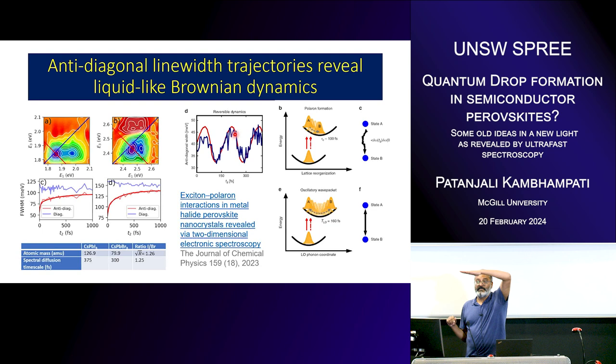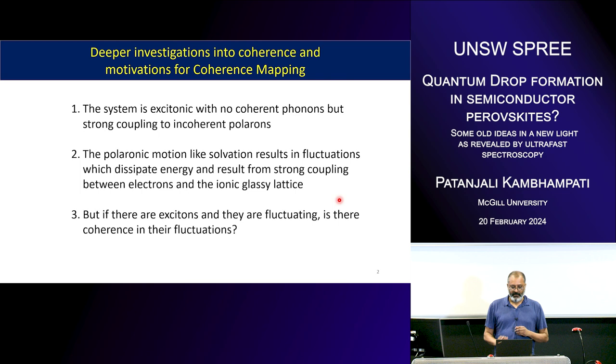So the perovskite goes from the ground state to the excited state, the free energy surface evolves diffusively, and then finds its minimum, like a liquid. The quantum dot undergoes coherent wave packet motion. So we have incoherent motion that's diffusive for the perovskite. We have coherent motion for the cadmium selenide, which is different, which is the contrast.